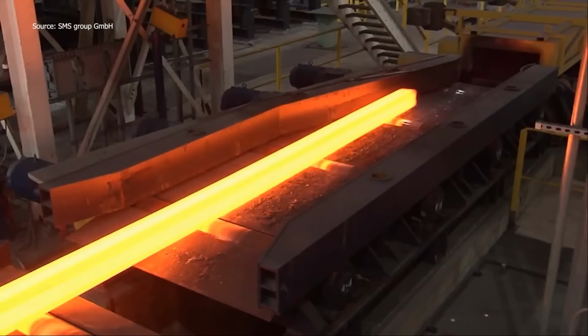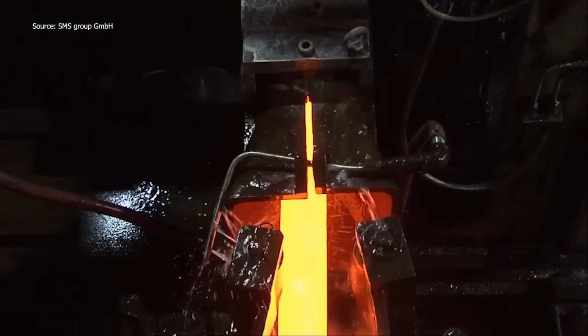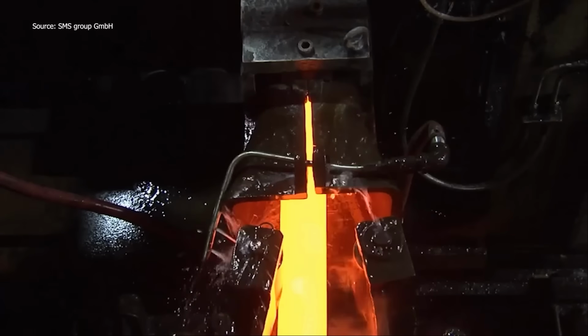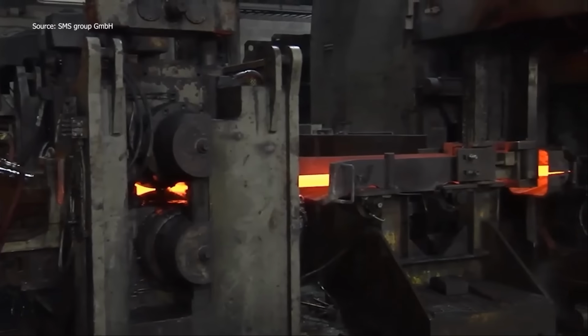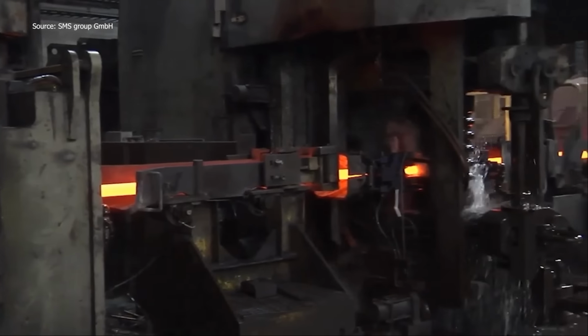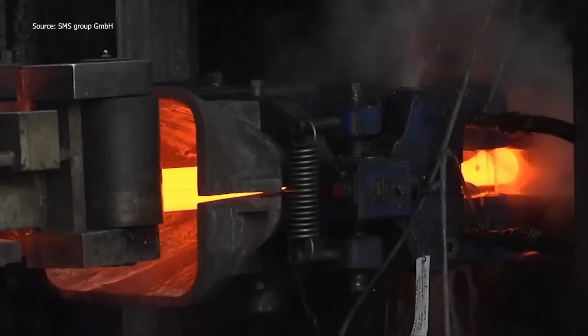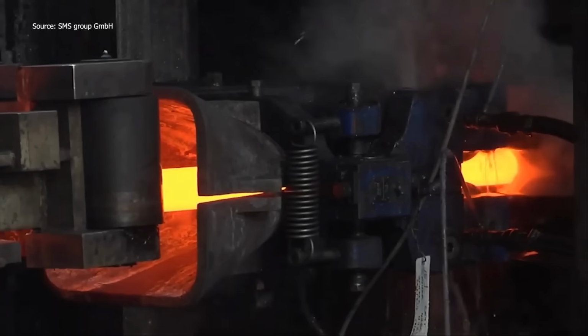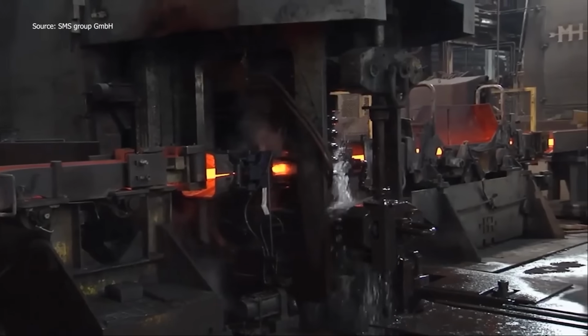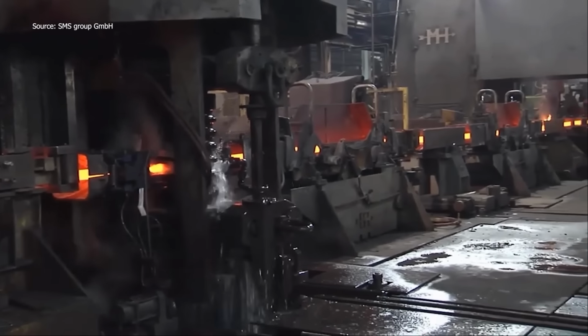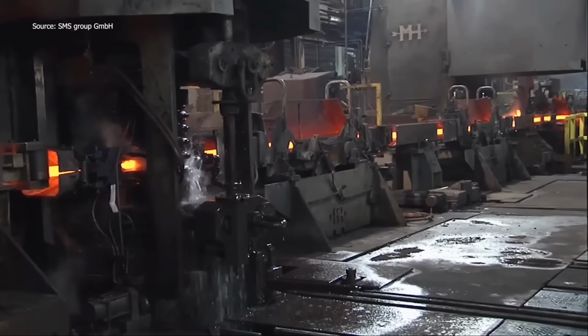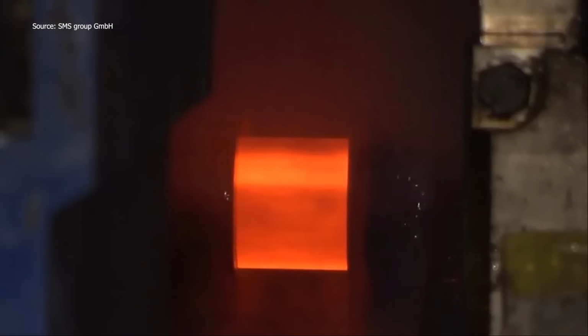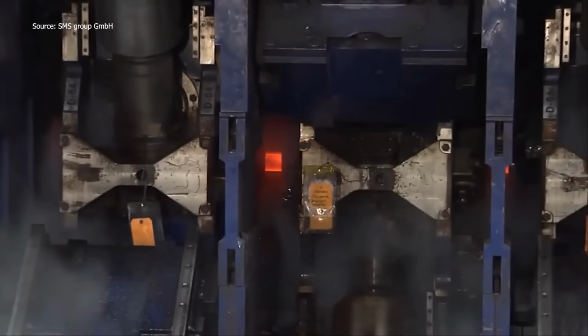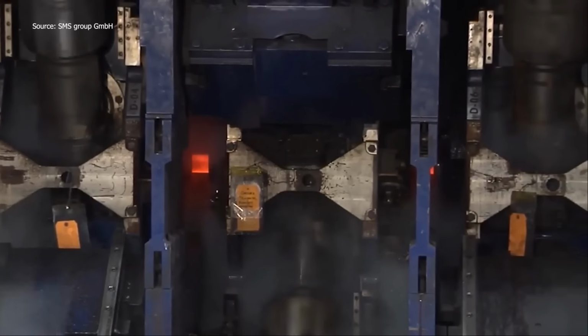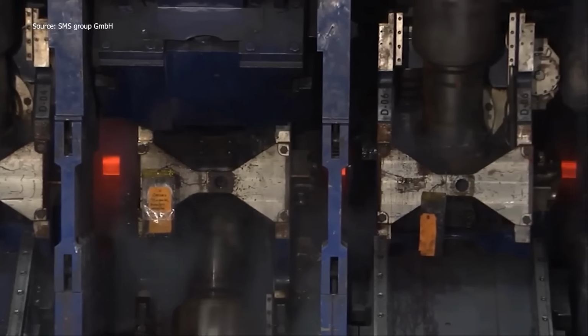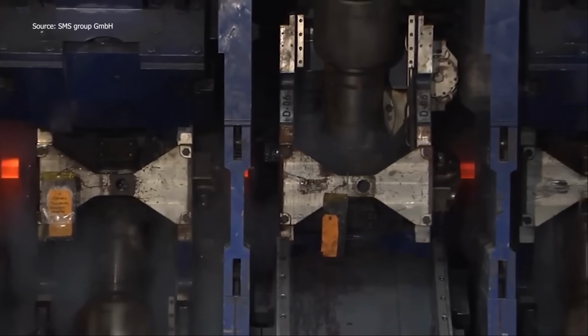You can almost feel the heat radiating as glowing billets move between each pass. An insulated roller table preserves heat before the bar reaches the next 4 housingless stands in an HV arrangement. The ends are cropped for uniformity, and the rolling continues with tight interval stands to fully utilize thermal energy. A carefully designed 90-degree roller table transfers material to the existing finishing mill without surface damage. Every detail, even in material transfer, is engineered to avoid defects.